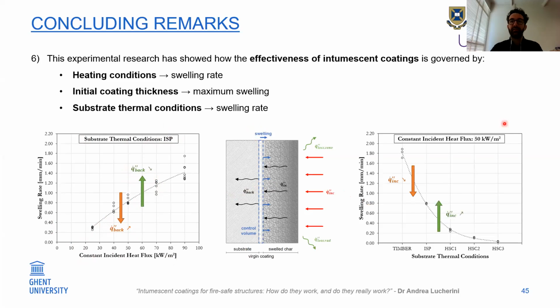On the other side, if you have the same incident flux, the same heating conditions, and different substrate conditions, so a very insulating substrate like timber, or a heat sink with a very high flow of water, so a lot of losses, you can imagine that the swelling rate decreases because all the heat is mainly dissipated and doesn't reach the swelling coating. And if you increase the incident flux, you get a higher swelling rate. Instead, if you decrease the incident flux, you get a lower one.